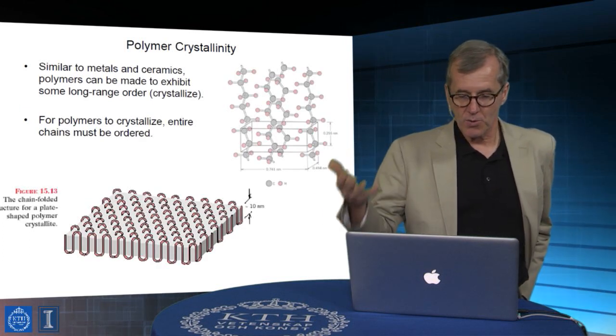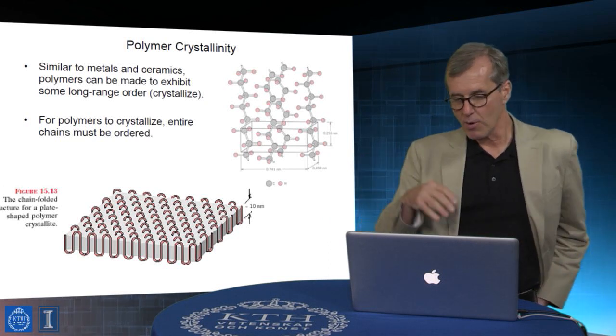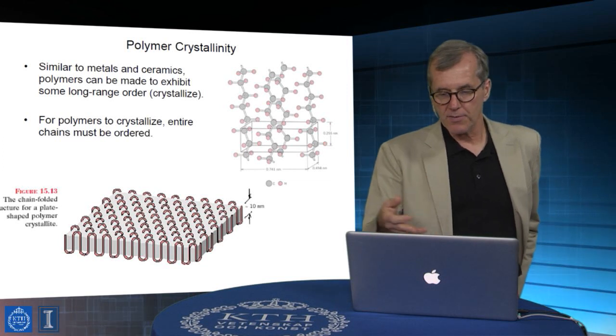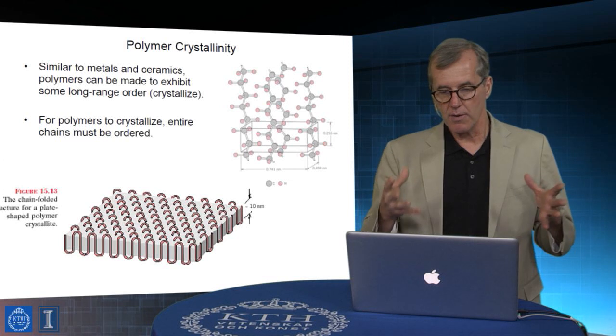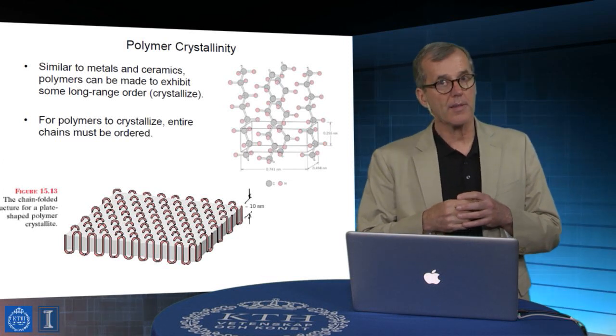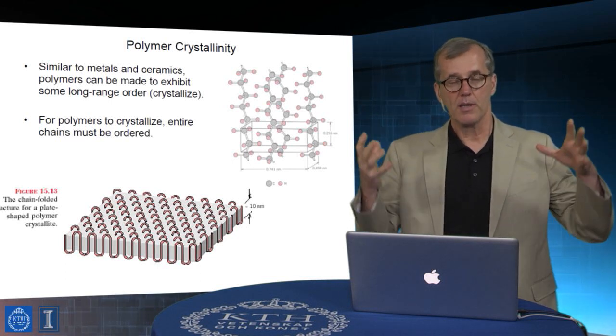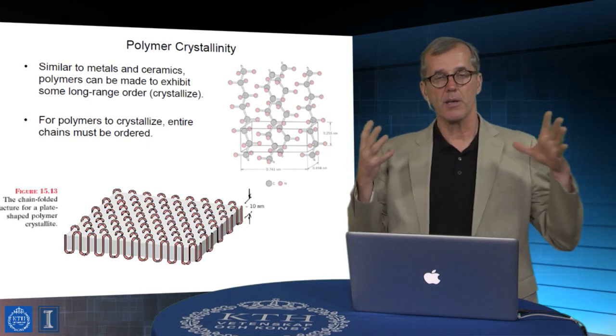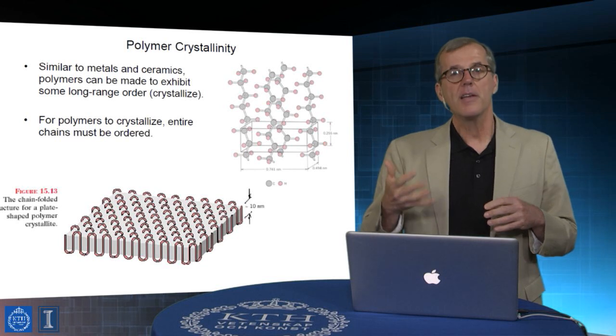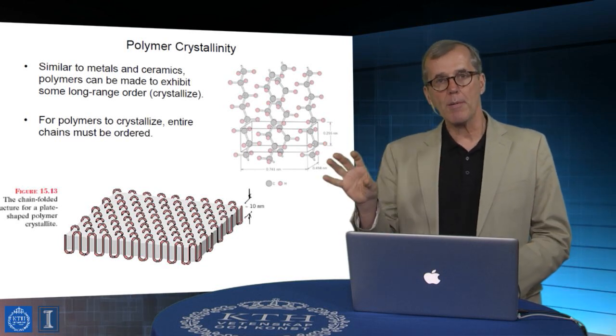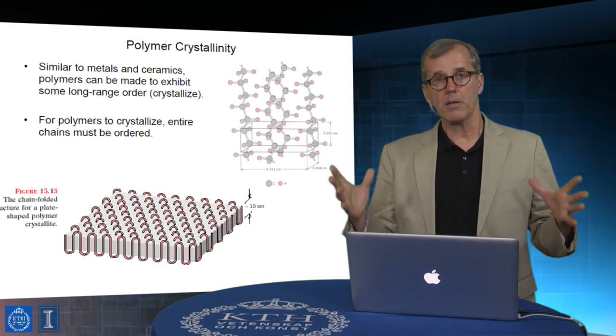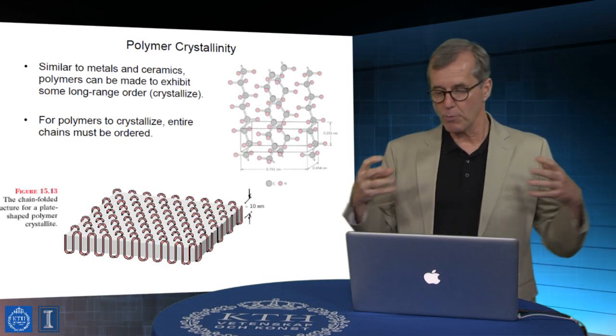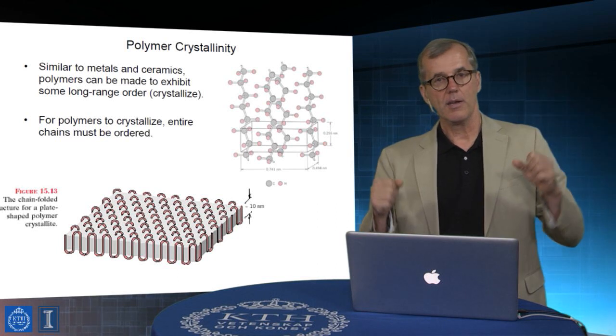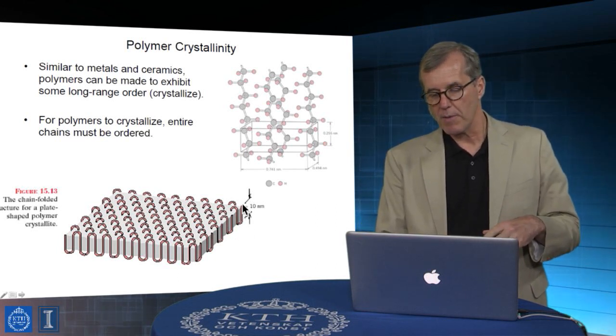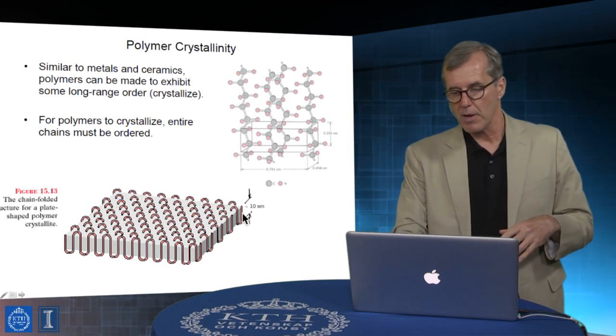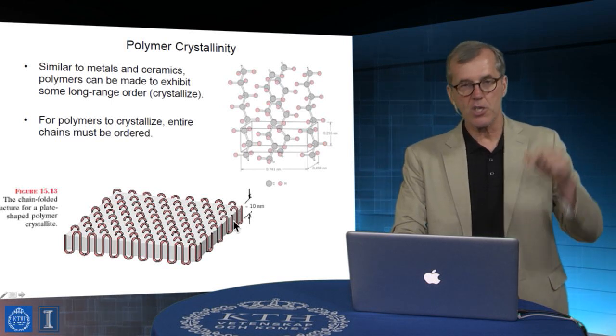And part of what's interesting about crystallization versus amorphous character or semi-crystalline behavior has to do with how it is that polymers actually get into crystalline forms, and part of it has to do with the fact that it's sometimes very difficult to get a very big molecule to completely organize in an ordered habit. And so they tend to get stuck, even though thermodynamic preferences would be to have a material go completely to its most stable configuration. So it would be great to have very thick lamellae, and that's actually shown as 10 nanometers. That might be a characteristic distance that will form a lamellar sheet, which then has to have a chain fold to inject the chain back in that sheet.